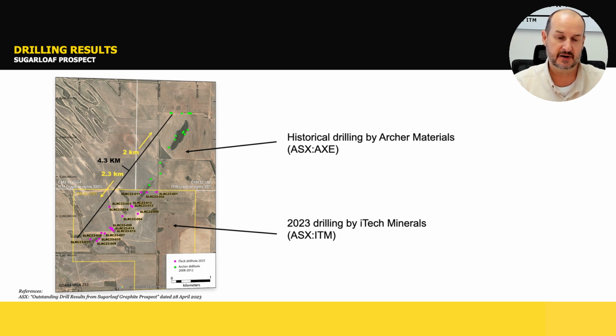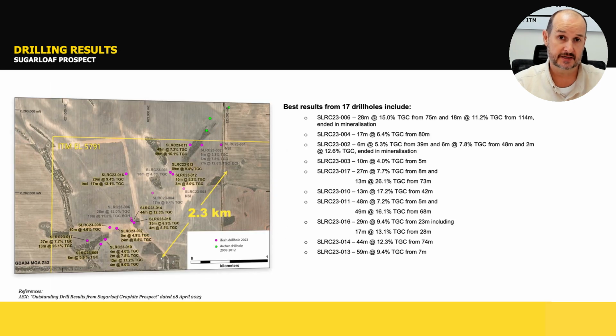Over a period of about a month, we've drilled about 17 holes in the southern half of that prospect, and I can present the results of that to you now. We were able to increase the strike extent of that mineralisation from 2 kilometres by a further 2.3 kilometres. And we got some really nice graphite intersections at Sugarloaf in that southern 2.5 kilometres. Some of the really significant intersections, and this is just in one hole, we had a top part of 48 metres at 7.2% from just 5 metres below surface, and then a lower horizon of 49 metres at 16.1% from 68 metres.